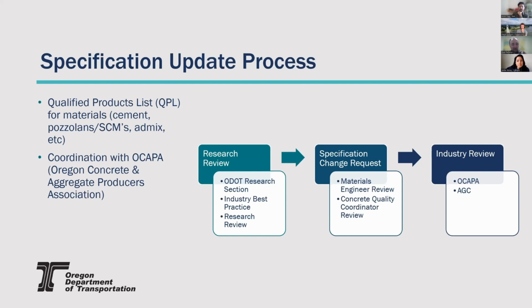A lot of our high performance concretes have a prescriptive, not just the minimum cement content, but a prescribed pozzolan content, whether it's a slag or a fly ash, and that's driven by the ASR reactivity of the aggregates. So if you're going to use a potentially ASR reactive aggregate, you need 15% by weight fly ash or 20% by weight slag. And you have to balance that with now a Type I cement that doesn't meet your established water to cement ratio, and it also has a pozzolan in it. So you have to balance the equation with what the specification already requires in the way of ASR remediation, and what kind of pozzolan is already blended into the cement that you want to use.